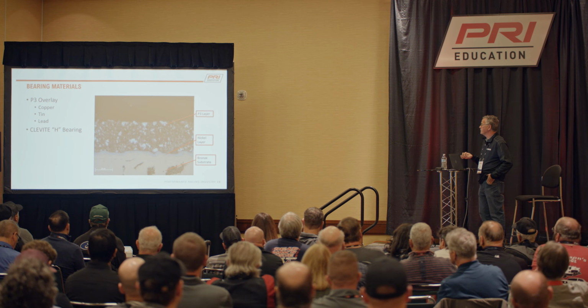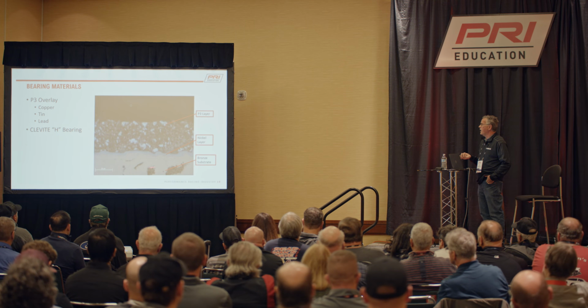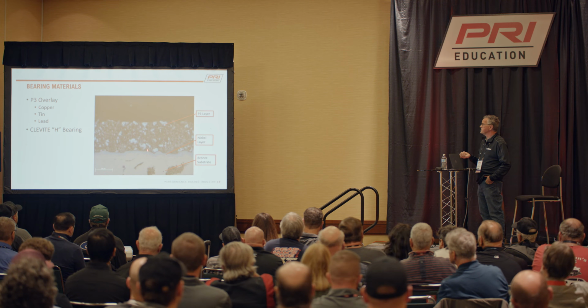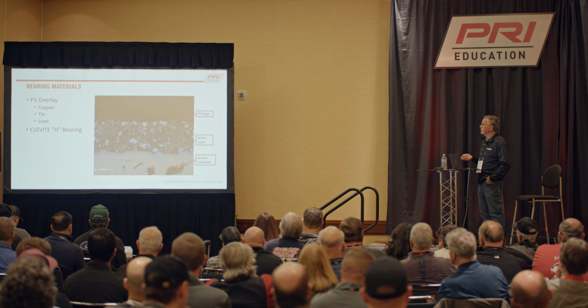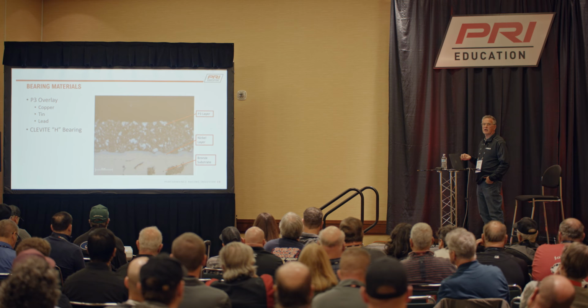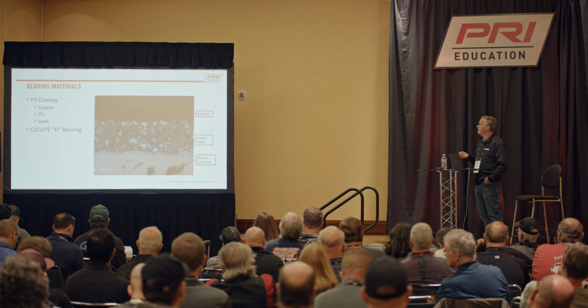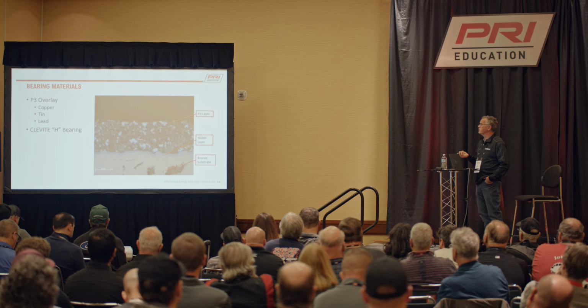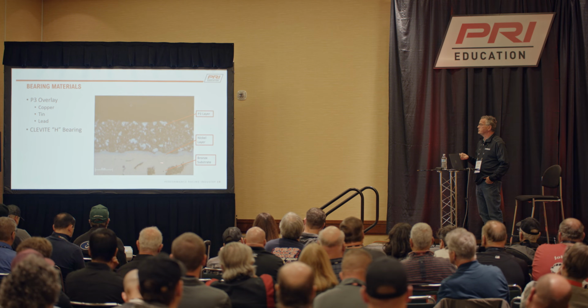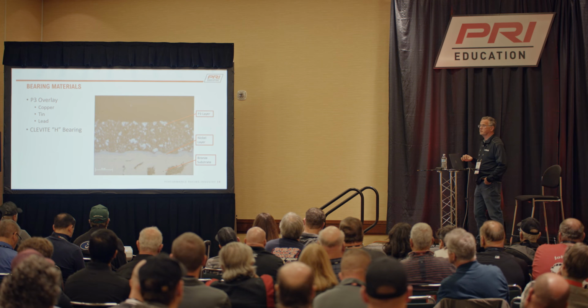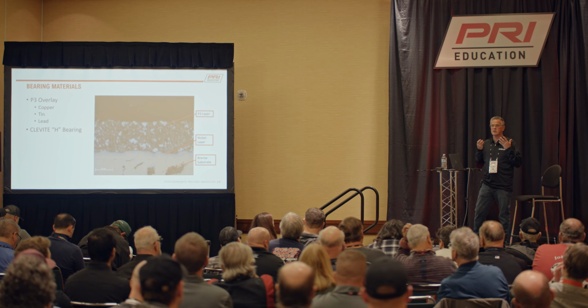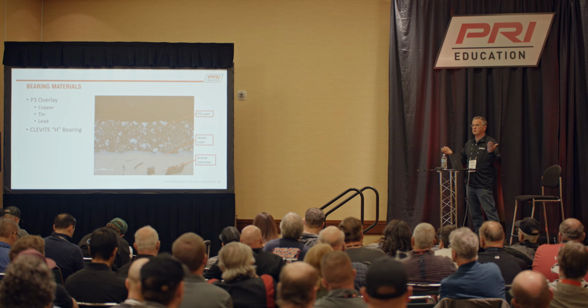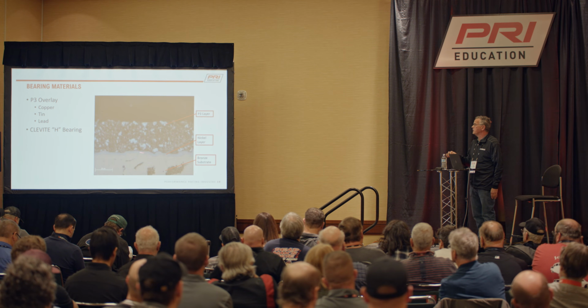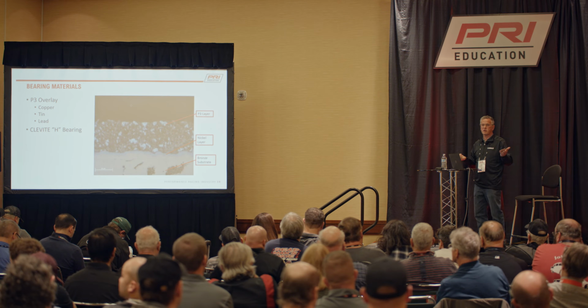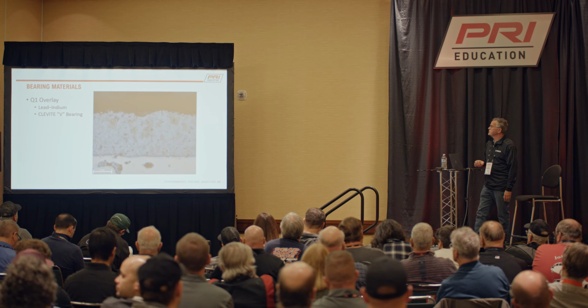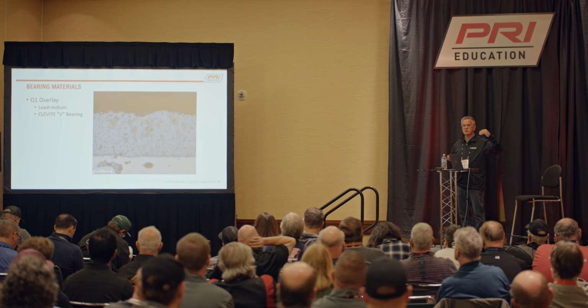So the overlay, as I mentioned before, there's a steel backing, which would be down here. This is a microscopic view of it. There's a bronze substrate, and any copper tin lead will have to have a nickel layer to keep the plating from migrating into the substrate. The plating process, the natural tendency is it will plate into it, so you have to create a couple micron, 3-4 micron layer of nickel, and that just creates a barrier.